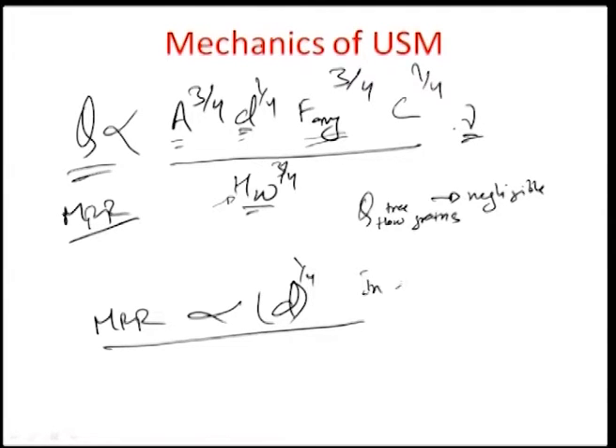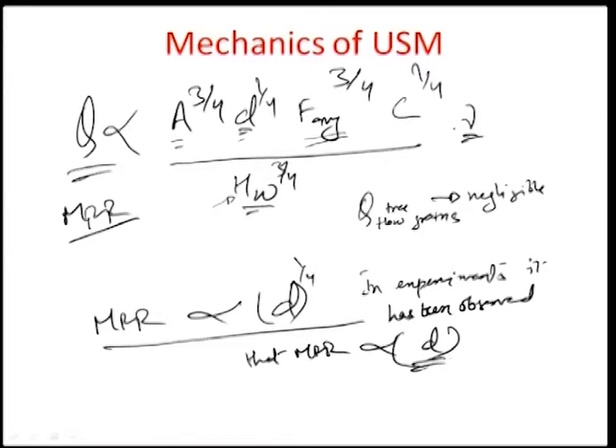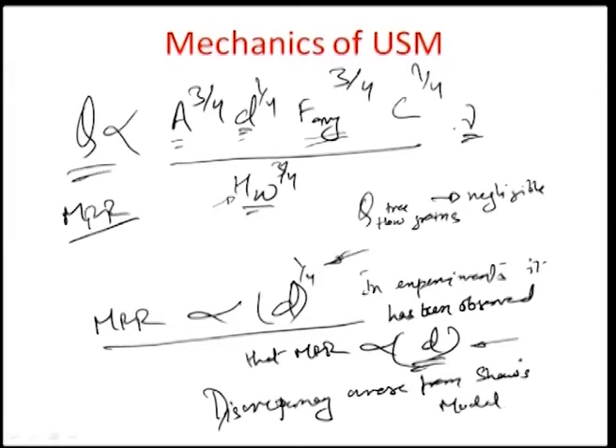Unfortunately, that is not so, because in experiments it has been observed that the material removal rate is proportional to the first power of d and not d to the power of 1 by 4. So this was a discrepancy that arose from the Shaw's model, because of which some explanation needed to be given, so that this experimental data, which comes out proportional to d, could be fit with the data theoretically derived by the Shaw's model. So Shaw tried to find out what actually happens in reality. This discrepancy was addressed by Shaw finally by looking at the overall shape of the grain.